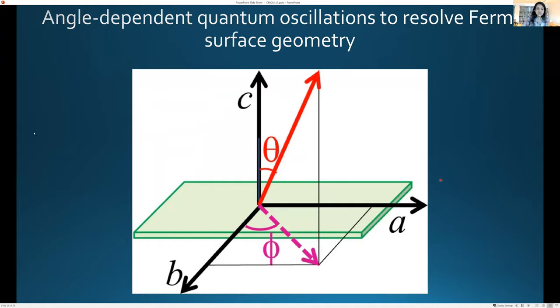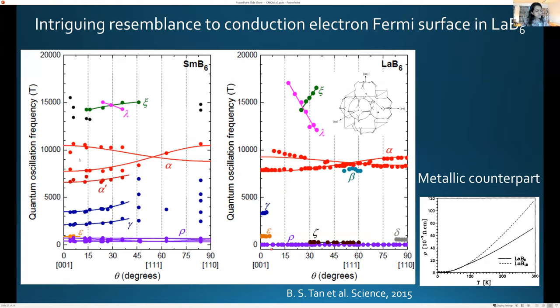Okay, so this is now the quantum oscillation frequency as a function of magnetic field angle. You can see that not much changes with angle. This is just a regular scale, it's not a log scale, so you can see that nothing much changes. We're looking especially at the highest frequency oscillations.